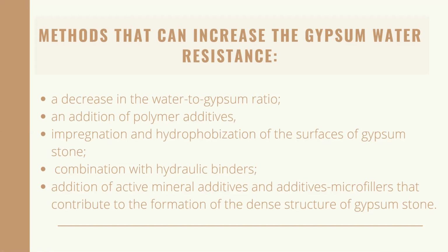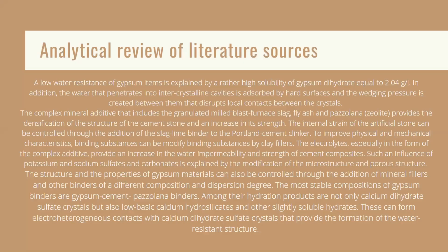of gypsum stone. During the studies carried out to improve the compositions of gypsum binders, the water resistance was evaluated by the softening factor, the compression strength ratio in the water saturated state and initial dry state. Hence, the studies of the volumetric strengths of artificial gypsum stone with mineral additives and their relation with the water resistance are an important task.